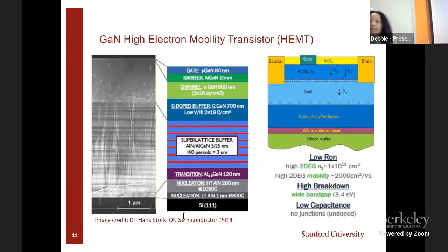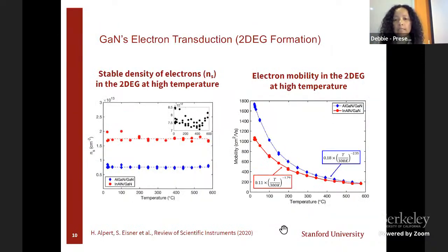This is a cross section of a high electron mobility transistor, HEMT, so I'll start to use that terminology now. Our GaN HEMT, high electron mobility transistor. We do a lot of work to be able to grow it on silicon. We use a silicon 111 substrate to lattice match as much as we can, and then we grow a series of interfacial or buffer layers to enable integrity of the AlGaN/GaN layer. This would be our device layer up here. So we have our AlGaN/GaN, and then our two-dimensional electron gas, and then these are called strain relaxation layers. So, strain engineering, preventing strain relaxation. In our strain engineering layers, we're slightly grading the dopants in order to transition so we don't get cracking or strain relaxation in our two-dimensional electron gas.